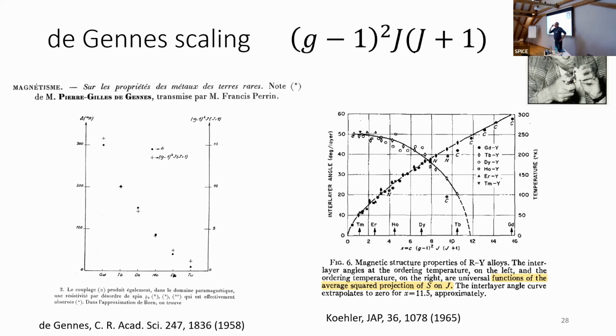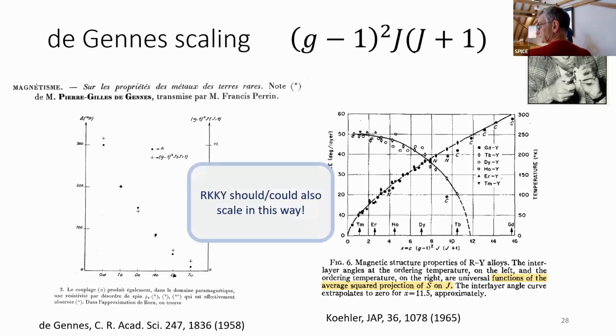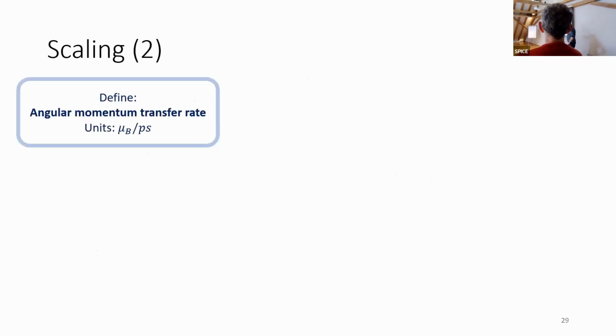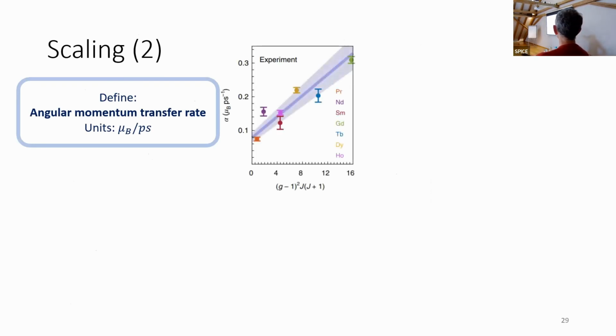So the conceptual understanding that we want to have in the back of our minds is that if we have a dynamic process and some sort of rate, in our case, angular momentum transfer rate, it should scale with the strength of the associated coupling. So we're going to define now an angular momentum transfer rate in units of Bohr magneton per picosecond and plot it as a function of the de Gennes factor. And we find that it's actually pretty linear. This is for one fluence, all fluences work. And I was very happy with this already.